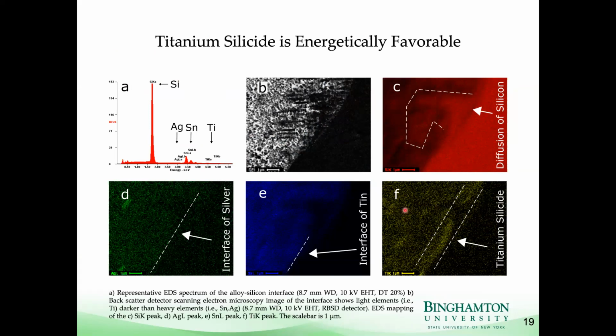And most importantly, we see titanium. So there's a kind of diffuse cloud of titanium everywhere in the metal alloy, but you can see there's a brighter region of titanium near the silicon interface. And we think that this is titanium silicide. It looks like it's about 1 micron from this scanning electron microscopy image, but it's actually quite a bit smaller, we think, because this elemental mapping technique has a relatively large interaction volume for SEM. So we can't really resolve how small it is.